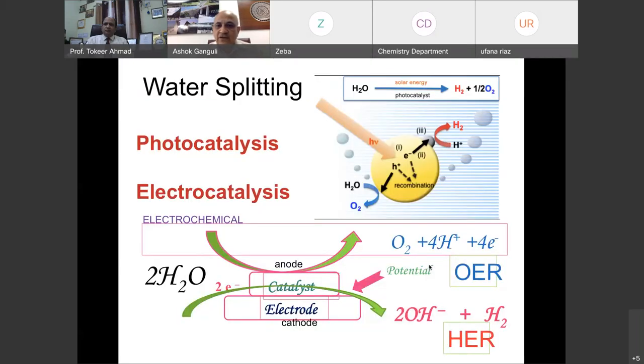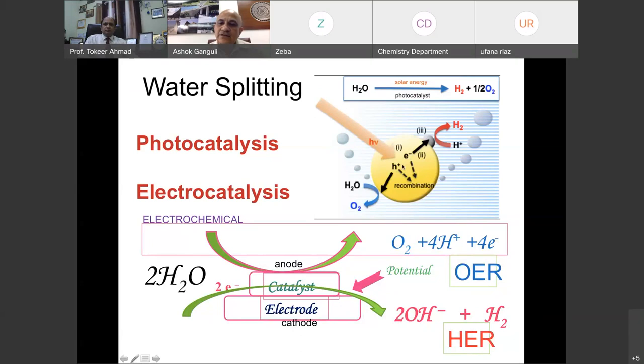Under AM 1.5 conditions, you get this kind of variation of wavelengths, and a large number of wavelengths fall in the visible range. That is why you want to work with visible light photons — the maximum number of photons are in the visible range, with some in the near infrared and close to UV. UV photons are only 4% of the solar spectrum, whereas visible light photons are 43%. So you want a semiconductor that can absorb visible light photons.